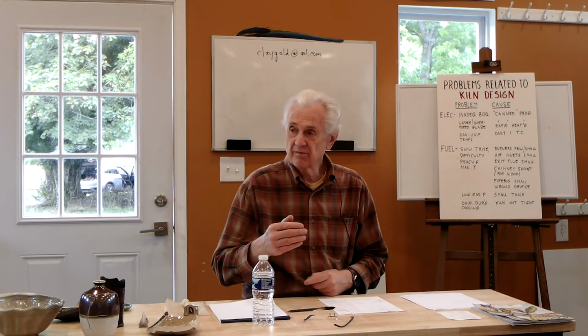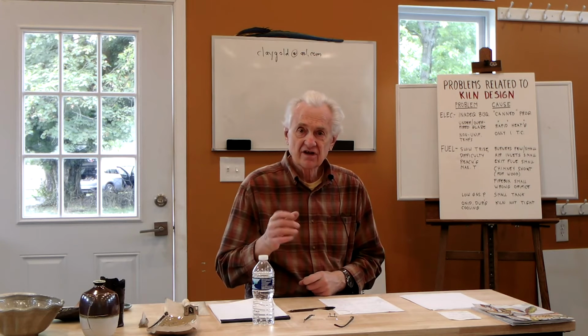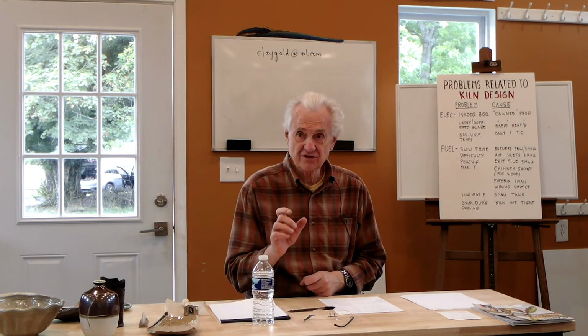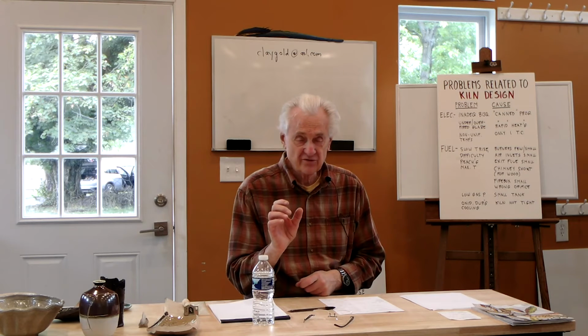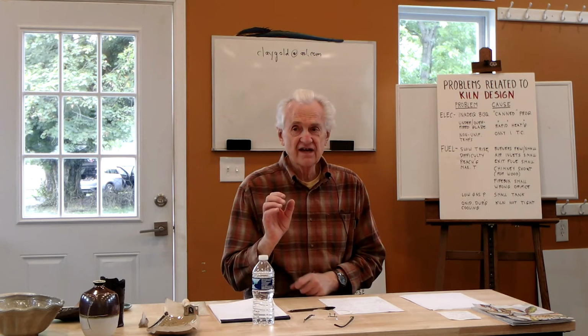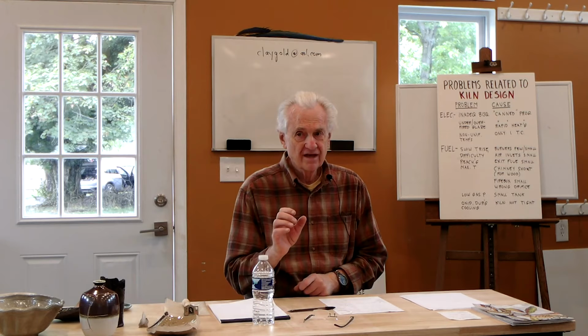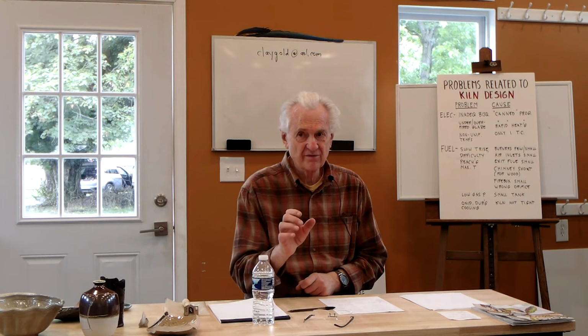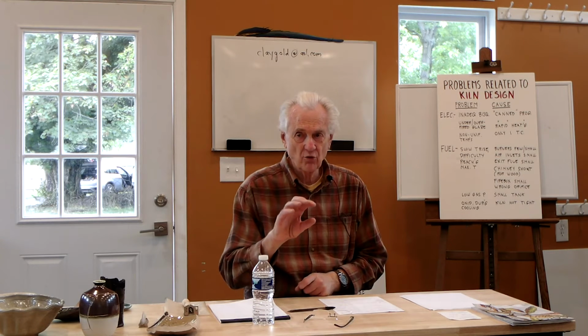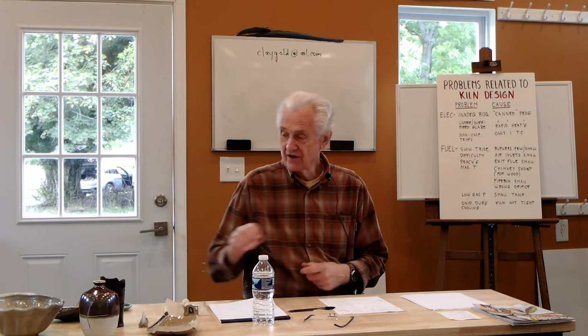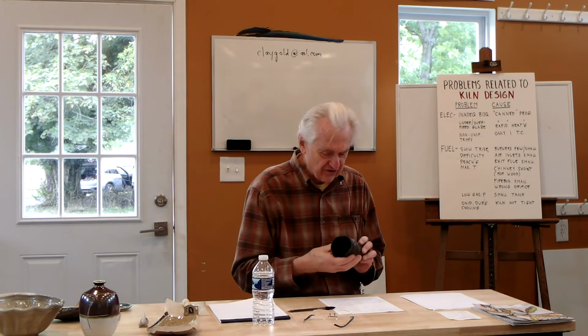Which sounds strange, but because cones are sensitive to time and temperature, the combination is what cones respond to. So if I have less time, then in a sense I need more temperature to make the combination work the same for a cone. And I'll pass this around. This is a good example.